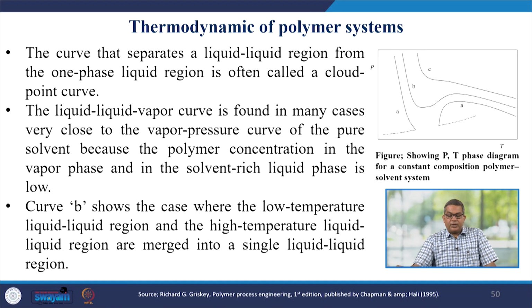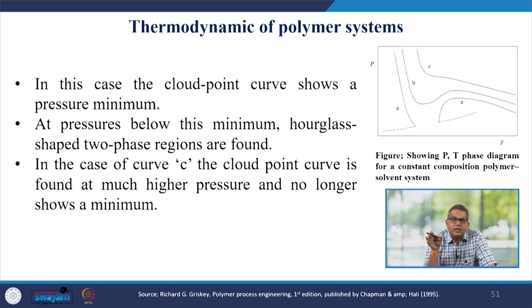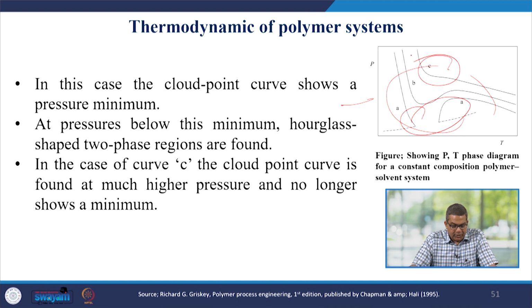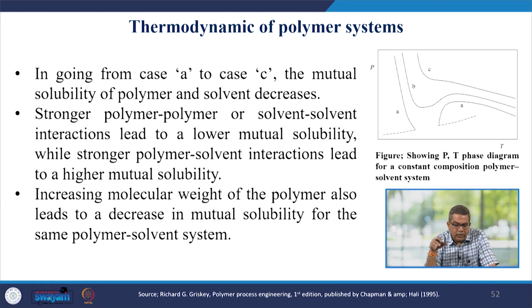Now, the curve that separates the liquid-liquid region from the one-phase liquid region is often called a cloud point curve. The liquid-liquid-vapor curve is found in many cases very close to the vapor pressure curve of the pure solvent, because the polymer concentration in the vapor phase and in the solvent-rich liquid phase is low. Now, in this particular case, again the PT diagram shows a pressure minimum. At pressures below this minimum, the hourglass-shaped two-phase region is formed. Now, in the case of curve C, the cloud point curve is found at much higher pressure and no longer shows a minimum. Going from case A to case C, the mutual solubility of polymer and solvent decreases.